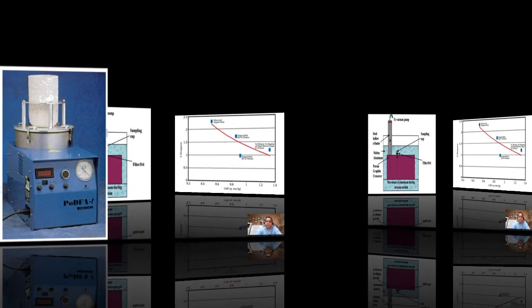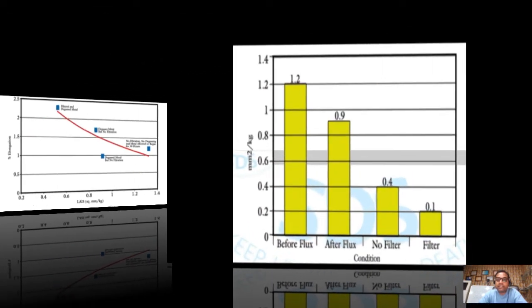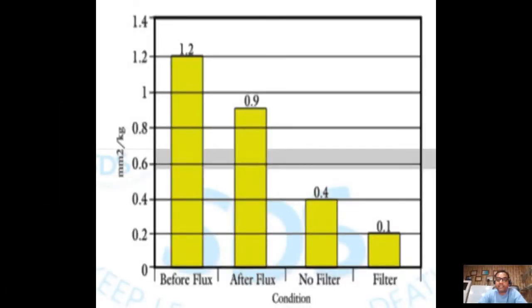Here is an example of the usefulness of these techniques. The LAIS method has been employed to evaluate elongation in 319 alloy as a function of several melt treatments. In another example, a die cast alloy melt has been examined using the PodFA technique before and after flux injection in a transfer ladle and also after subsequent filtration in a casting holding furnace — the validity of both melt processes in improving the melt quality is demonstrated.